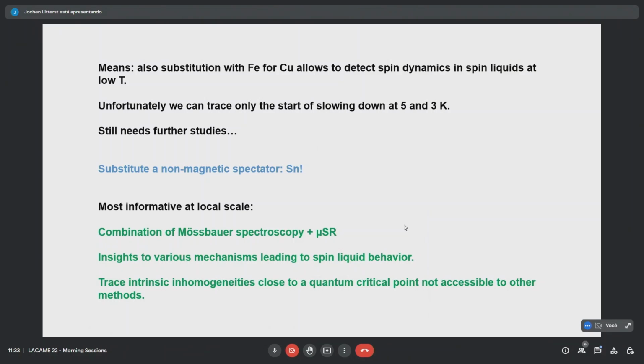So my proposition in this case: why isn't it perhaps possible to introduce not iron, which tends to cluster, and for which you already have these strong correlations at higher temperatures, but rather a non-magnetic spectator like tin? Dalbert spoke about that some days ago. I think it's more or less some kind of Mössbauer isotope, which I think is very valuable. So one has to try whether one cannot look at that. It's non-magnetic, it shouldn't disturb the spin liquid.